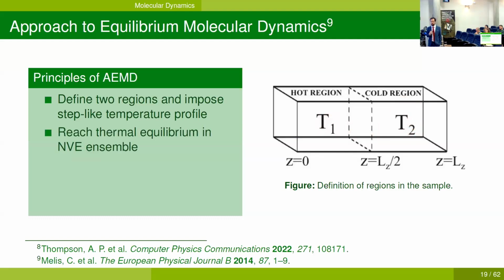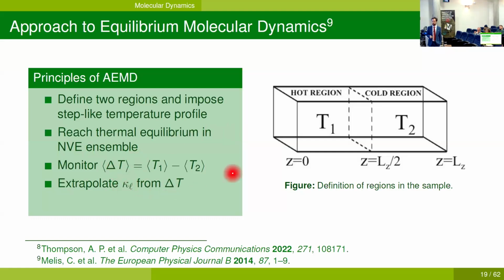Once we have this step-like temperature profile, we let the system reach thermal equilibrium again in the microcanonical ensemble, or NVE. While we do this, we monitor the average delta T between the two regions. And this delta T will, of course, decay to zero, and it will do so in an exponential fashion. From this exponential decay, we can easily extrapolate the kappa L. Basically, the faster the delta T decays to zero, the more conductive the sample is. We have implemented this with the LAMMPS software suite.